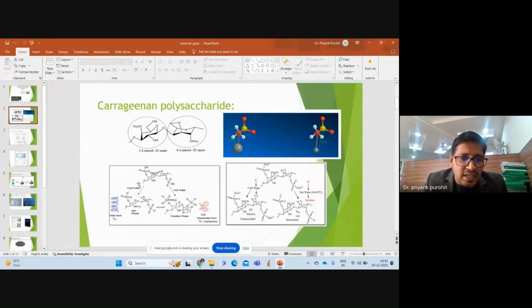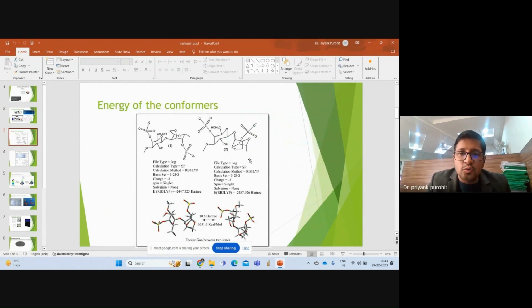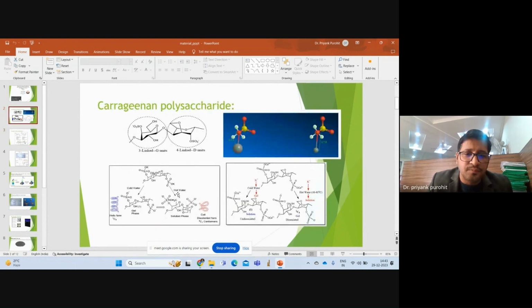As I discussed, this is the gel phase. Whenever we added some amount of heat, the conformational percentage changed from this to this form, this sulfated form. In that case, it was forming a solution phase because it was converting to the higher energy conformer. It is because of this linkage conformation.